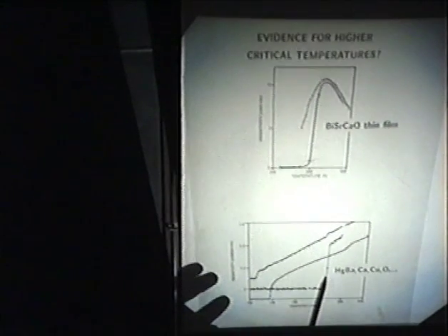And again here, another sample, this time mercury, barium, calcium, copper oxide. Transition temperature somewhere above 220 Kelvin, but unfortunately you warm it up and cool it down, it didn't do it anymore. But this is very tantalising, that maybe there are higher temperature superconductors out there, and maybe one day we will see a superconductor that will work at a useful field at even room temperature.